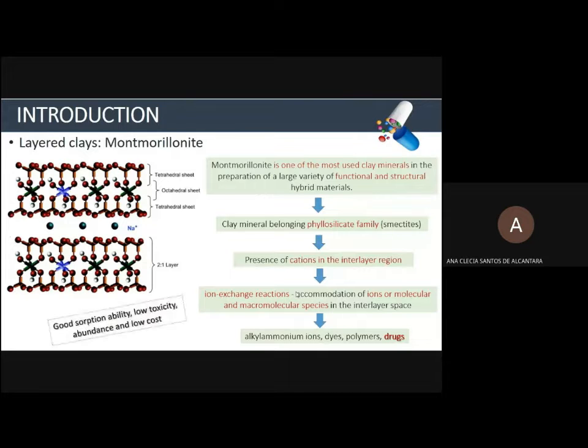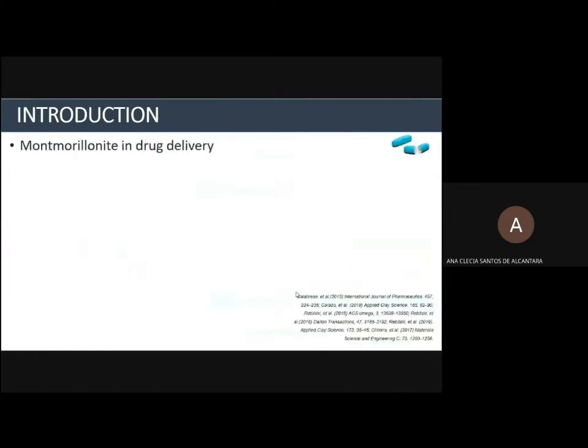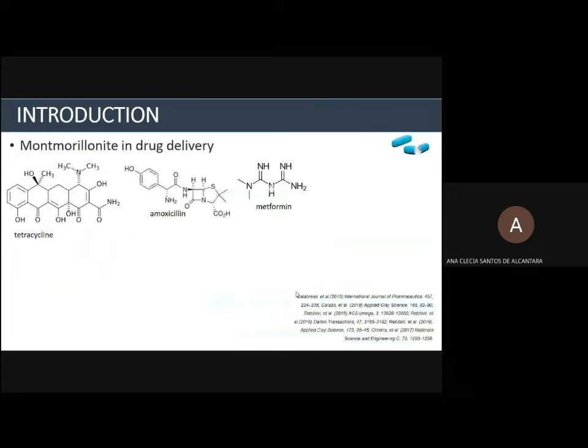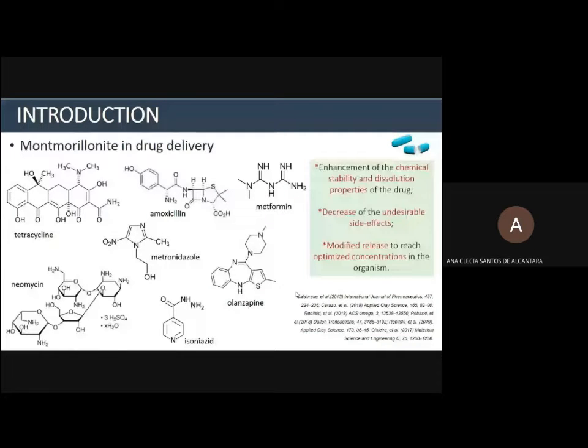In the case of drugs, montmorillonite is a very interesting vehicle because it shows good absorption ability, low toxicity, abundance, and low cost. In this sense, montmorillonite is used as a carrier for many drugs such as tetracycline, amoxicillin, metformin, metronidazole, neomycin, isoniazid, and olanzapine, for instance, where the intercalation of the drug in the interlayer space enhances the chemical stability and the dissolution properties of the drug, and consequently decreases undesirable side effects due to the modified release to reach optimized concentrations in the organism.